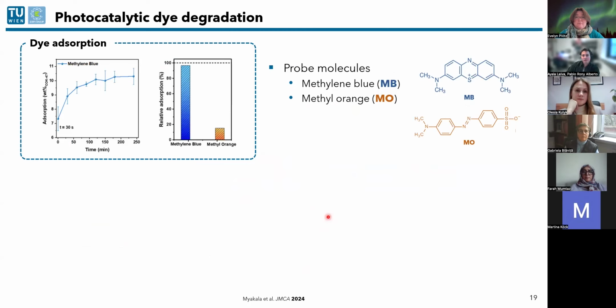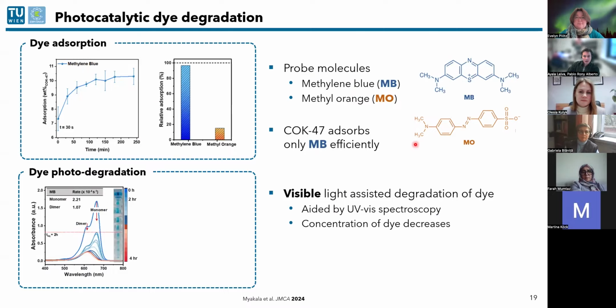In this second application, we are using probe molecules. These are persistent dye molecules that would stay in the wastewater for very long if we don't remove them. We use methylene blue and methyl orange. What we can see here is that COK-47, this particle that we made, was absorbing methylene blue quite efficiently. After absorbing it, we want to photodegrade these molecules. We do this with the help of visible light, because we know it's visible light absorbing. And then we follow the drop in concentration by UV spectroscopy.